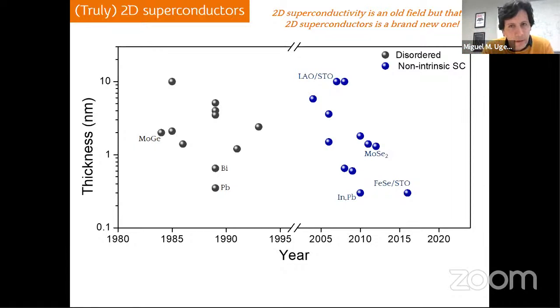Also, some interfaces were discovered which resulted in superconductors, or even MoSe2, monolayers of MoSe2. The problem with all these superconductors, though, is that they are not intrinsic superconductors. So it means that they only show superconductivity because they are grown on a particular substrate, or they are on a device, etc. And that's a problem, because we want intrinsic superconductors regardless of where the material is.